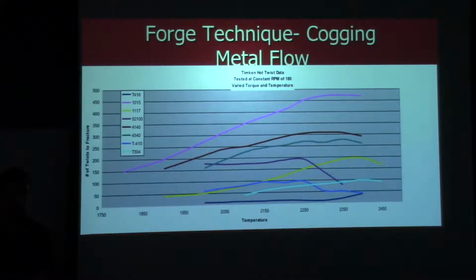We do that on purpose because if you had free sulfur, it makes the steel very difficult to do any kind of plastic deformation, forging or rolling. The steel tends to crumble. Years and years ago, it was hard to get sulfur out of liquid steel as the steel industry was developing. They found that they could put manganese in and deal with the sulfur that they were having a hard time getting out. And so then you had material that you could use. You could forge it and roll it, whatever you want to do with it.